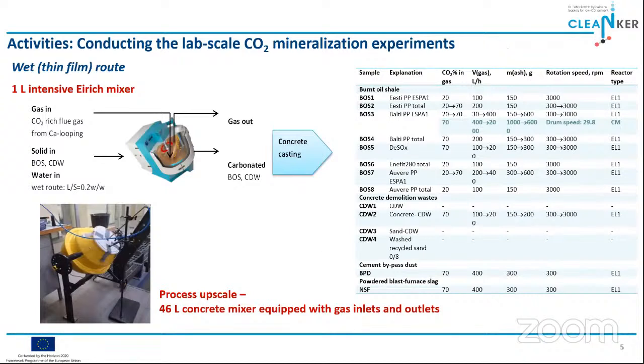As for the scale of the laboratory experiments, they were conducted firstly in a 1 liter intensive mixer using a low water to solid ratio of 0.2. Later, for process upscaling, a 46 liter concrete mixer equipped with gas inlets and outlets was utilized. Operating conditions such as CO2 content in the gas phase, rotational speed, and material flow were varied during the experiments in order to see the parameters' effect on the process.